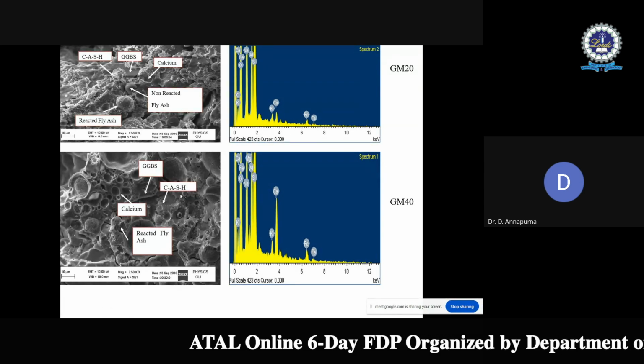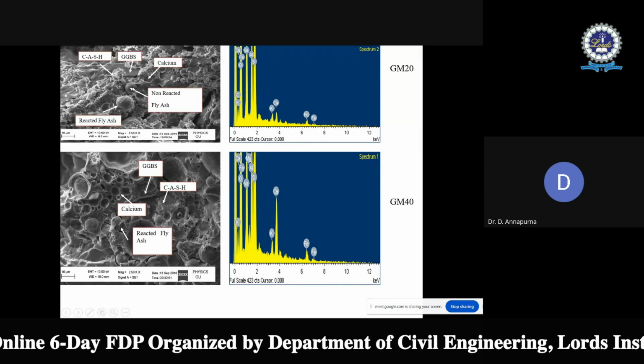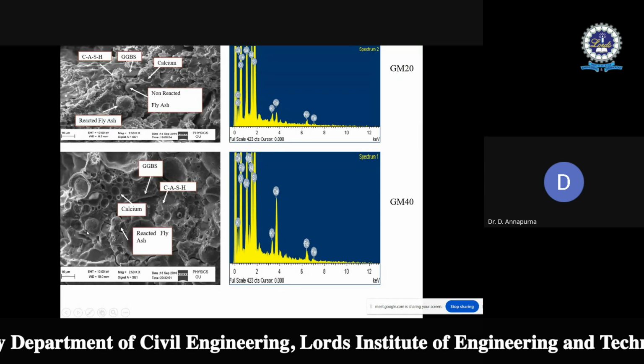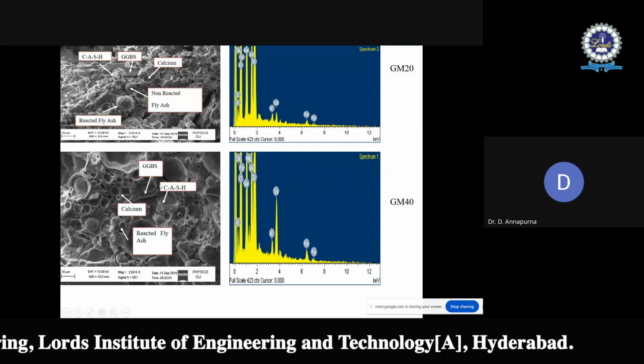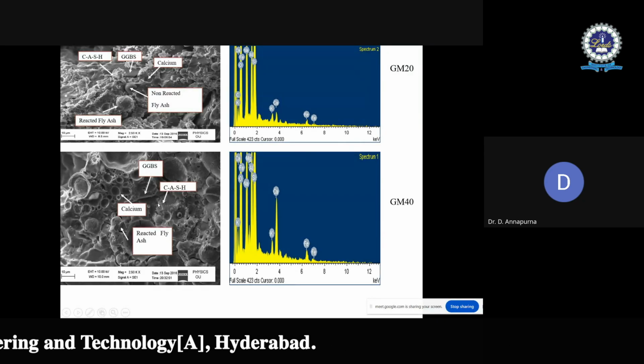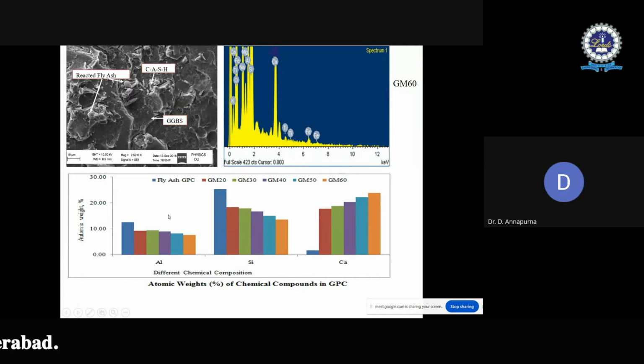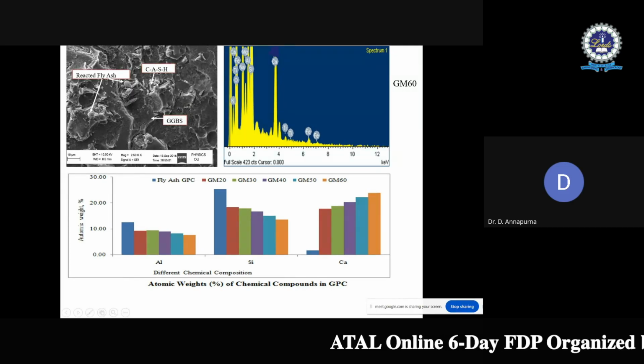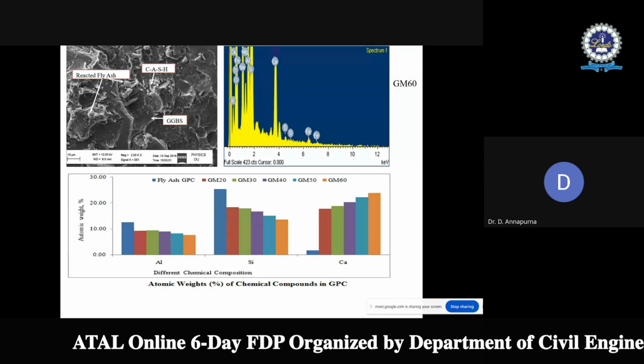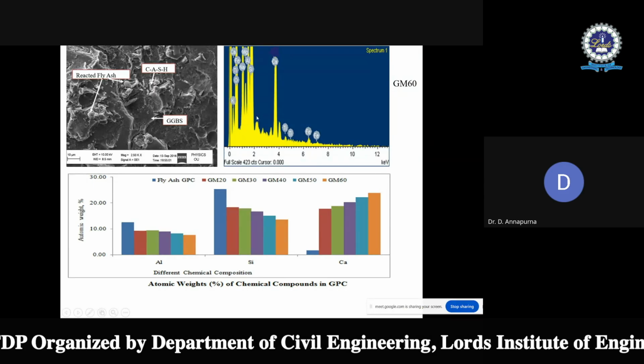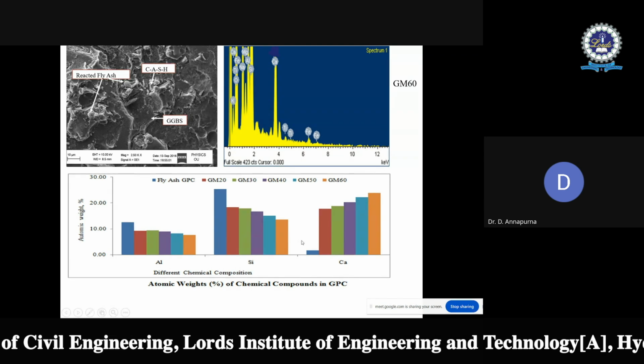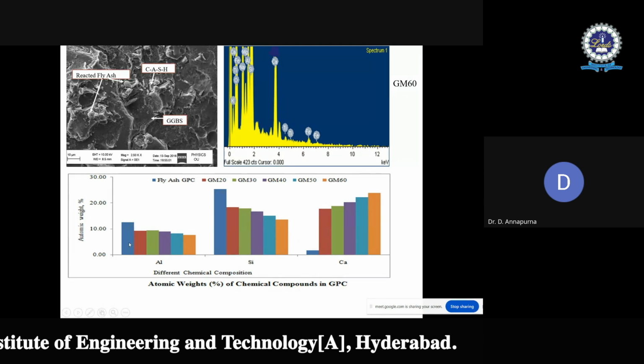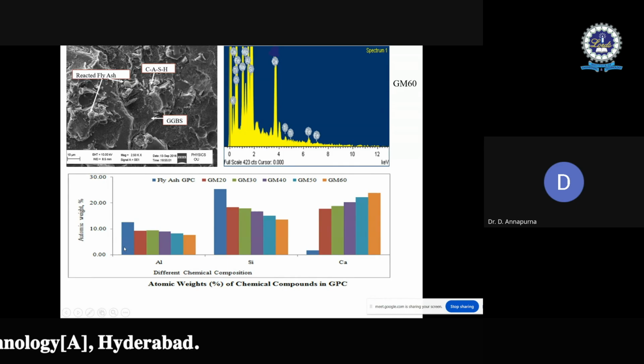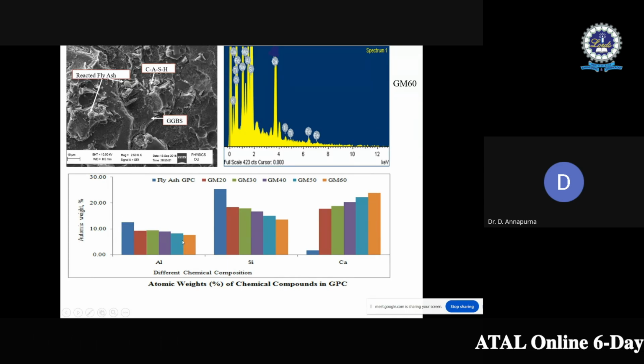Here we can see that in the case of GM40 also, more traces of reacted fly ash are there. Again GGBS is there, and calcium aluminate silicate hydrate gel formations are there. Again, the presence of calcium aluminate silicate hydrate and sodium aluminate silicate hydrate can be witnessed through these EDAX pics. From the EDAX pics, the percentage weights are considered. All the percentage weights are plotted for different types of mixtures. The first one is fly ash GPC, then GM20 to GM60.